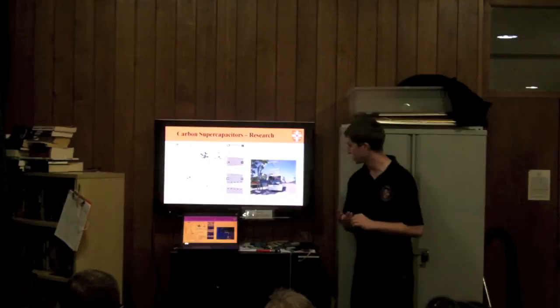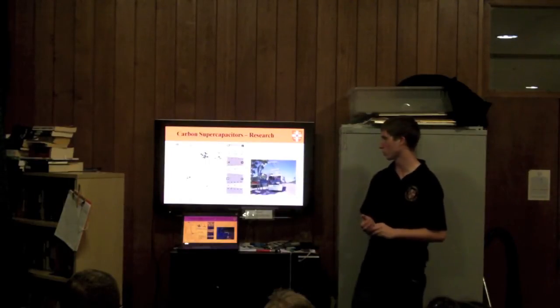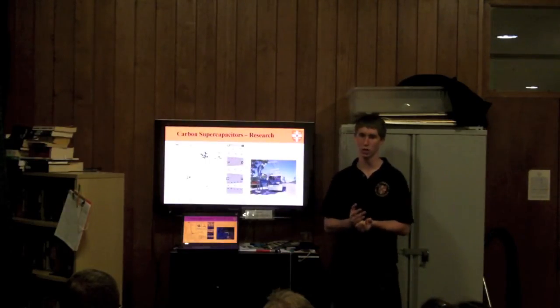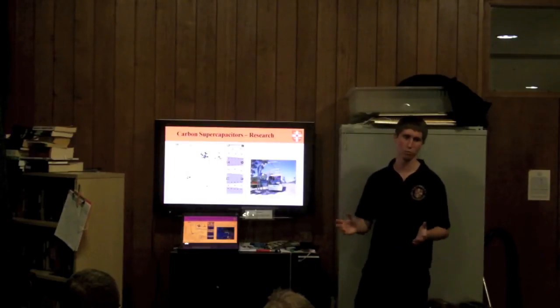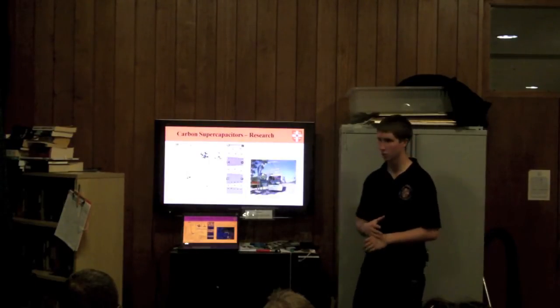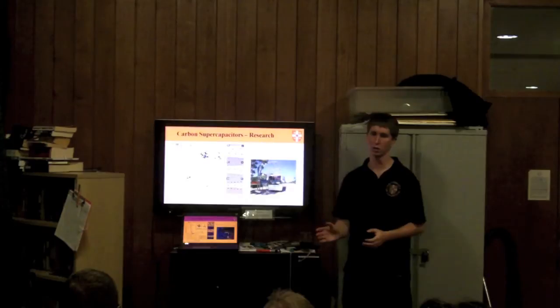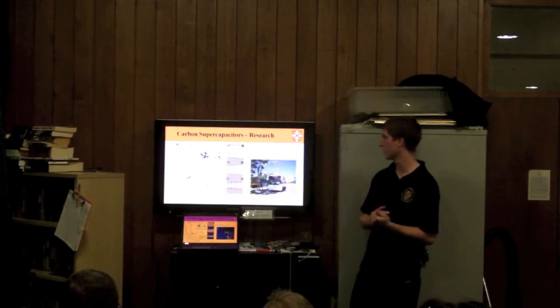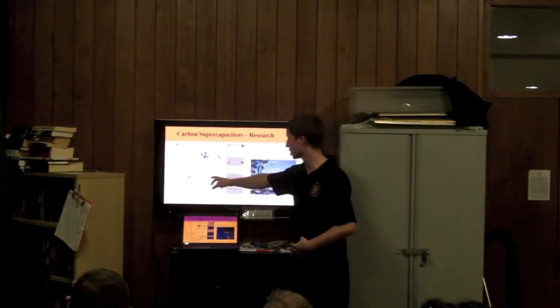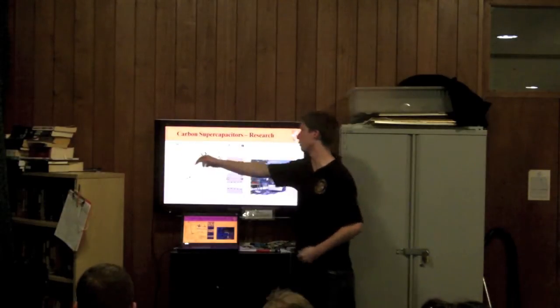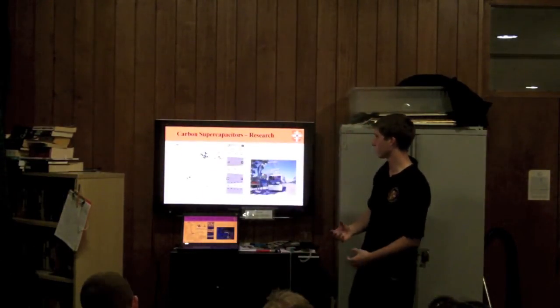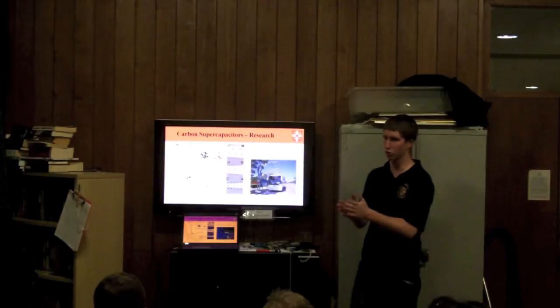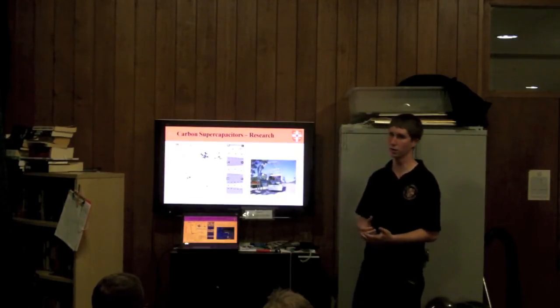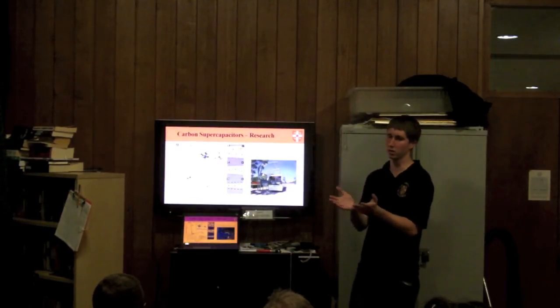What they found out though is if you use even smaller pores, less than 1 nanometer, which they thought the ions wouldn't fit in at all, so it wouldn't work, actually the ions will desolvate. They lose their solvation shell, which was pretty surprising, I think, at the time. And so that's why this whole traditional view was changed. The capacitance shot up in this red plot because as you get closer to the surface, the amount of charge that's stored is also higher. That's how a capacitor works, right?